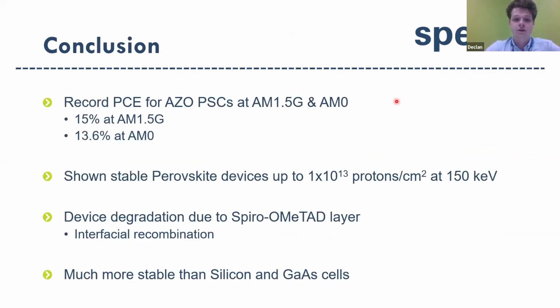For a conclusion of this work, I believe this is still the case. We recorded a record PCE for AZO devices: 15% at AM1.5G and 13.6% at AM0. The devices are stable up to 10^13 at 150 keV. We showed that the spiro-OMeTAD is the defining factor which limits device performance at higher fluences. Even at 10^13, the device performance and stability is still higher than unencapsulated silicon, gallium arsenide, and triple-junction cells. So it's still very good in terms of results.